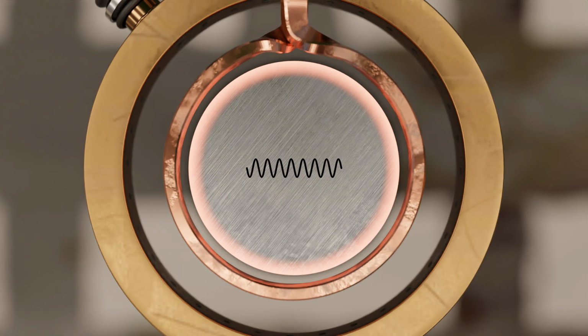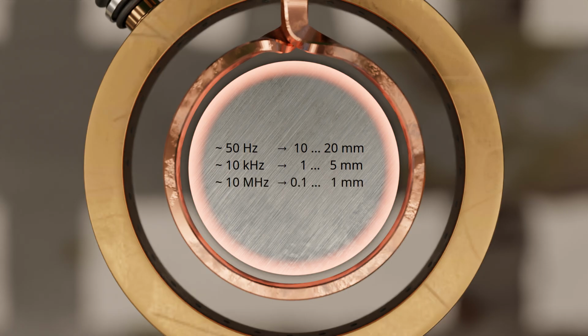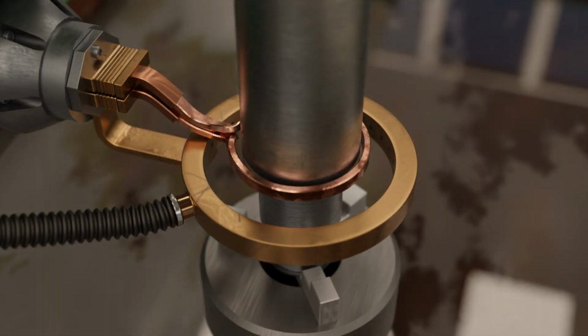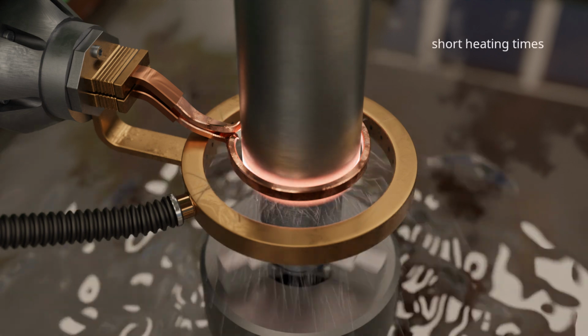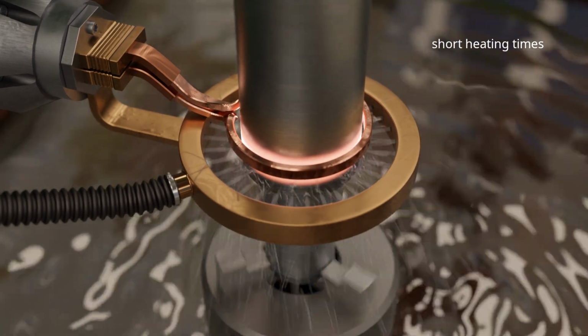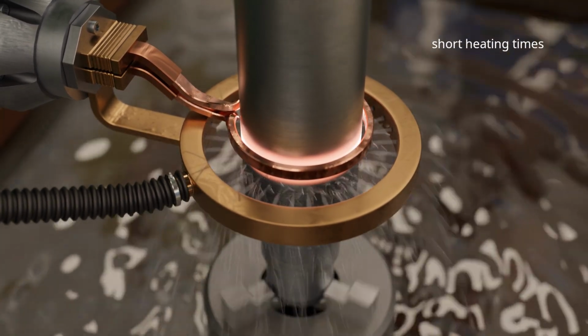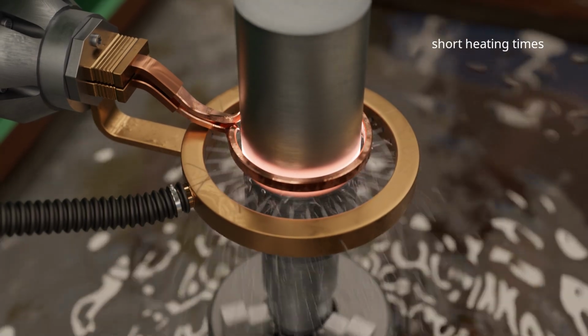At a frequency of 50 Hz, hardening depths in the range of 10 to 20 mm can be achieved. In the frequency range from 1 to about 10 kHz, hardening depths of about 1 to 5 mm can be achieved. In the high frequency range up to several megahertz, hardening layers as thin as a few tenths of a millimeter are possible. Heating times for induction hardening are generally much shorter than for flame hardening, as the specific heat output can be around 10 times higher at several kilowatts per square centimeter.